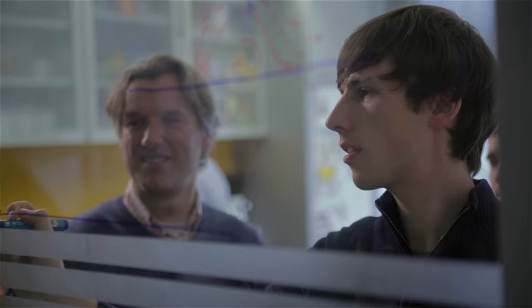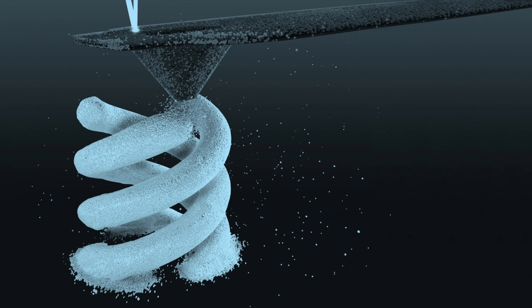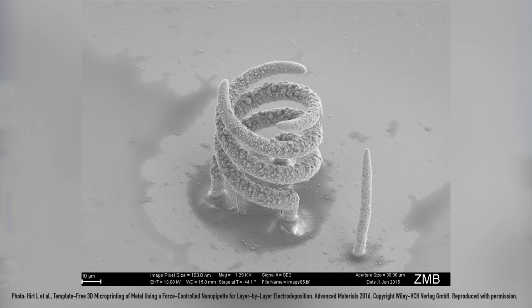When a material is released through the aperture and grows underneath, we observed that it touches the syringe, bending it. We took advantage of exactly this moment to regulate the process. As an example, we could even print metal microstructures via electrochemical reduction.